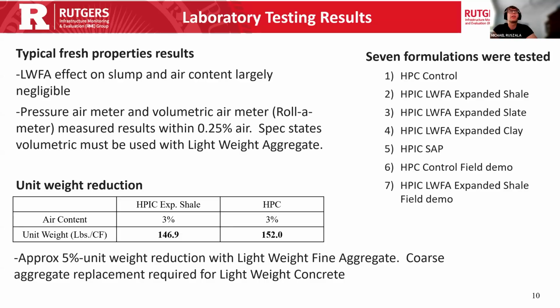So we found in all cases that the lightweight fine aggregate's effect on slump and air content was largely negligible. Finishability was very similar as well. Lightweight aggregates require a volumetric air meter. It's specified to, but we saw a very small difference between the pressure meter and the volumetric meter. Results are very similar. We suspect this is because there's a very small dosage of lightweight aggregate compared to traditional lightweight concrete formulations. And this kind of shows itself with the unit weight reduction. We saw a very minor reduction in the unit weight of the concrete. We are using a lightweight aggregate, but we're not using all that much of it, how you would typically use with a lightweight concrete, with it being a full replacement of the coarse aggregate.